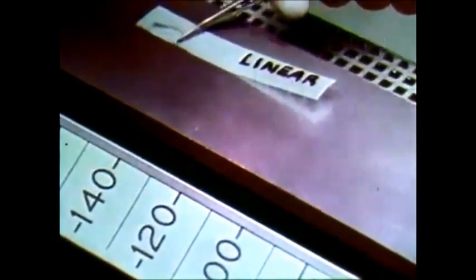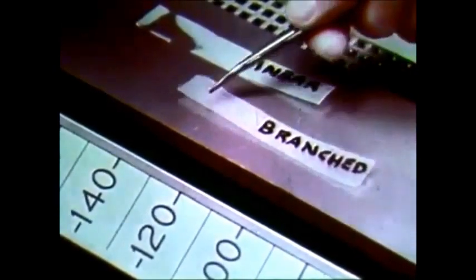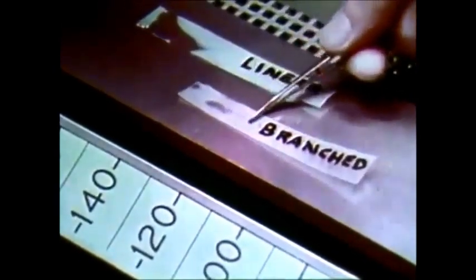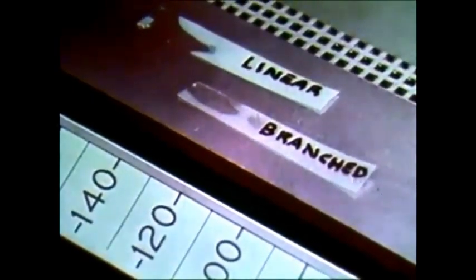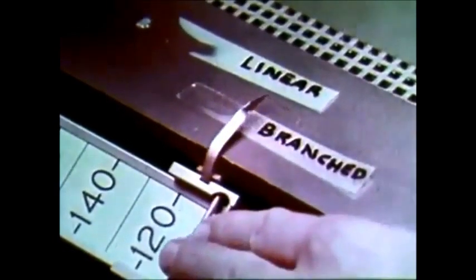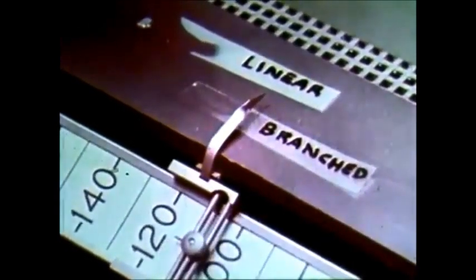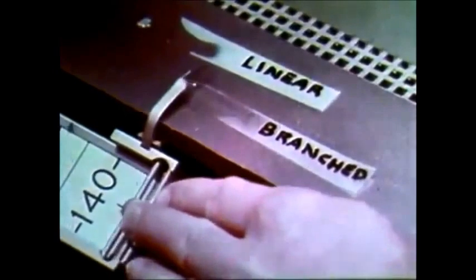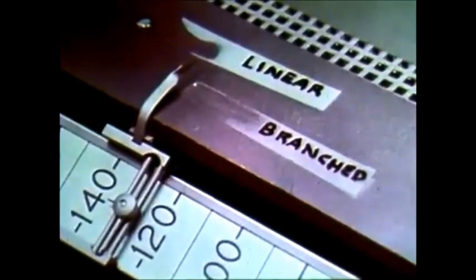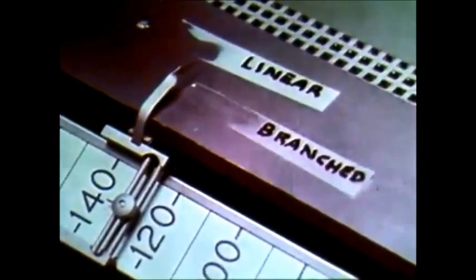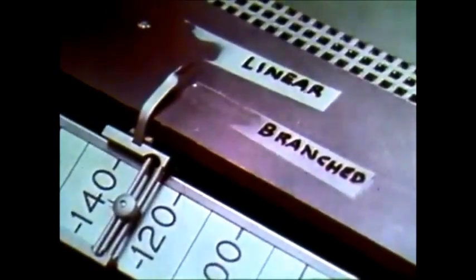For example, this linear polyethylene has more structural regularity than this branched sample. This material melts at about 115 degrees centigrade, 20 degrees lower than the linear polymer, because the chain branches inhibit crystal growth and also introduce imperfections in crystal structure.